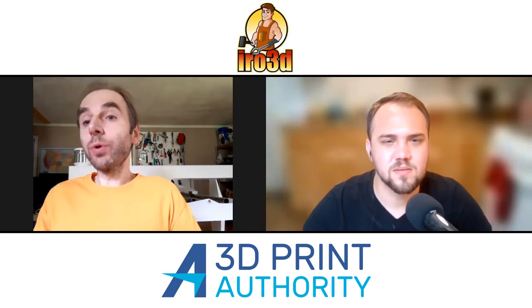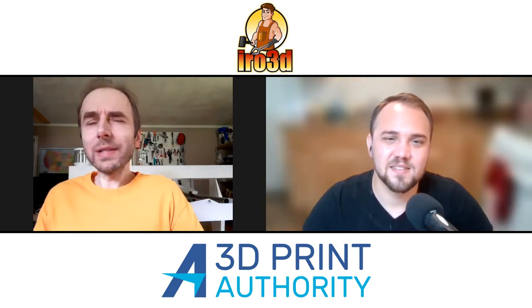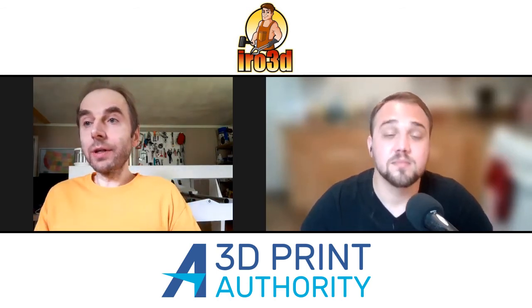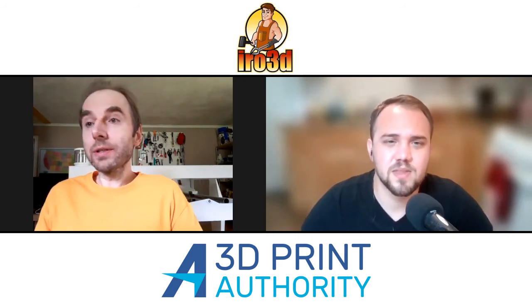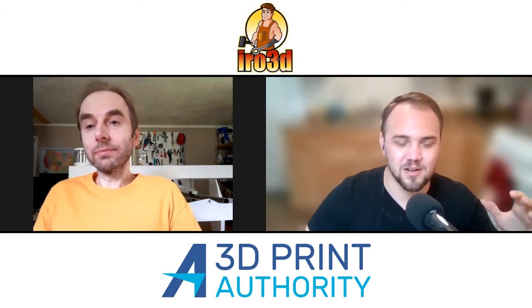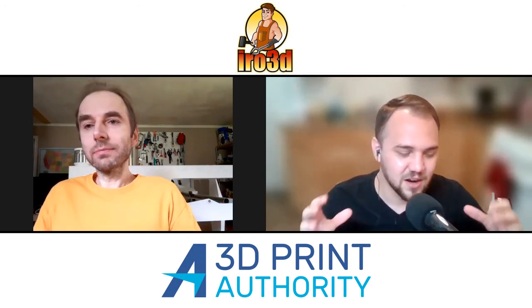There are ways they can improve it. They use hot isostatic pressing or something. They make it a little bit more dense, but it's still kind of complicated, and it's still not 100% dense. But this can be 100% dense, if your materials are clean, if they don't have any dirt or impurities that would generate some voids. Yeah. And it is very simple conceptually compared to these machines that cost over $1 million, and they have high-powered lasers and fine optics and all of this stuff.